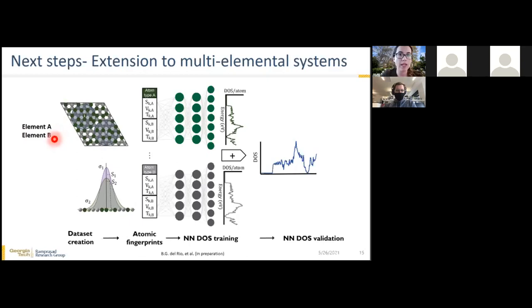And we calculate the fingerprints of each atom by concatenating the fingerprints describing the atomic environment created by atoms of type A to the fingerprints defining the atomic environment created by atoms of type B, for each type of atom. So each type of element will have its own submodel. That's why I put different colors here, with which we predict the density of states per atom for each one, obtaining the total density of states by summing all contributions.